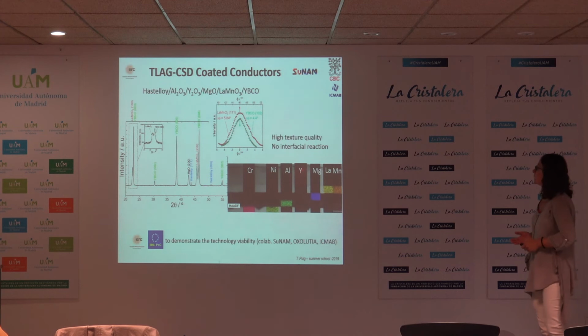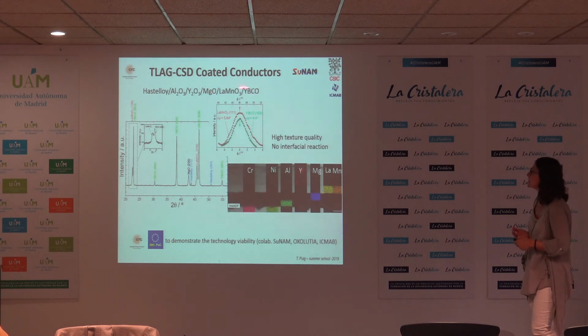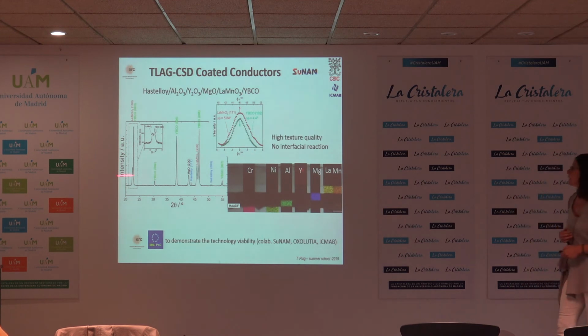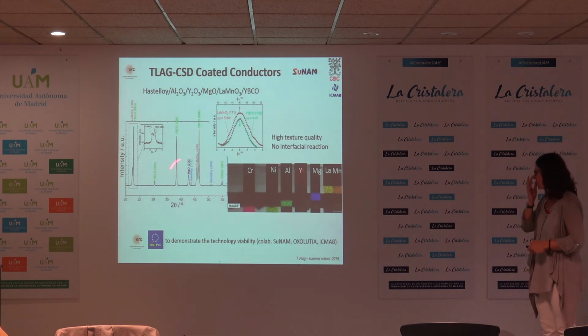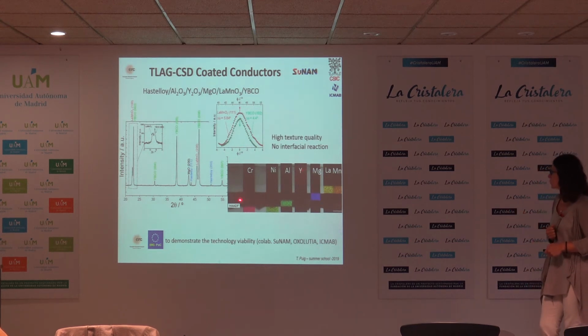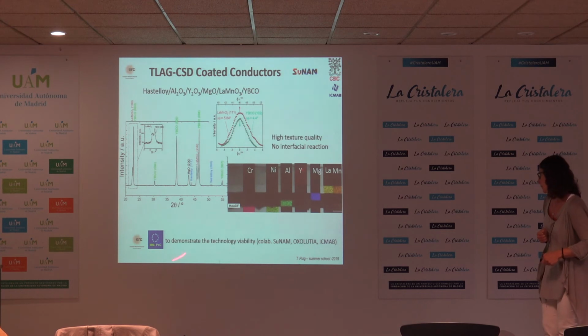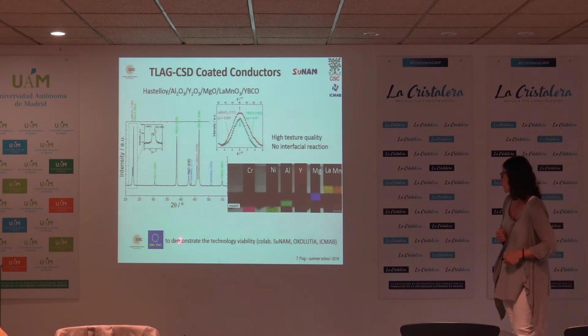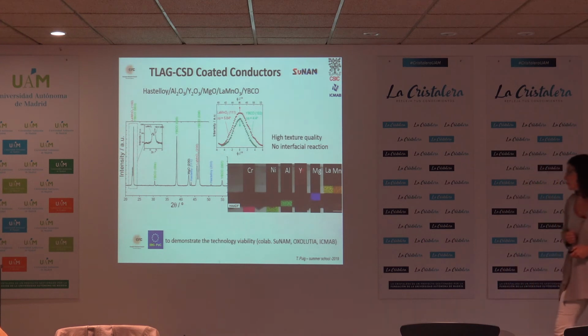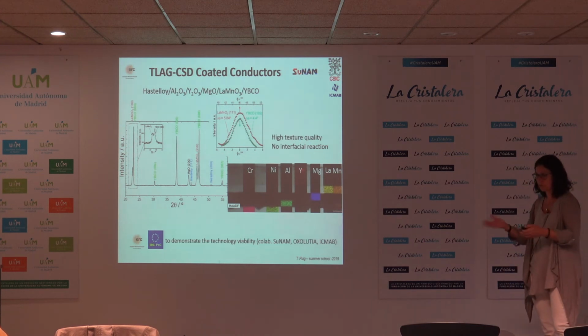We also have been able now to demonstrate that this process is compatible with a metallic tape, so with all the coated conductor structure, that we can grow YBCO epitaxially on top of the buffer layers that we have in the coated conductor before depositing the YBCO, and that there is no interfacial reactivity between any of the layers and also not with the YBCO. And now this has been awarded a proof of concept ERC project in order to demonstrate the technology viability of this process.